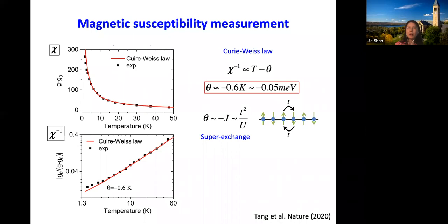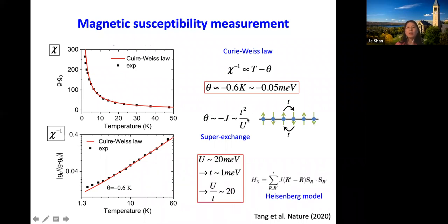We can put this back into the superexchange I discussed earlier for Mott insulator. So this magnetic interaction energy is on the order of t squared over U, right? And we already know U is on the order of 20 meV from the temperature dependence of the resistance peak. Theta or J now is on the order of 1 Kelvin. We can get t is on the order of 1 meV, and then U over t is on the order of 20. So this is in the strongly correlated limit, and this parameter t and U sort of agree with the Wu and MacDonald paper. So it seems to make sense.